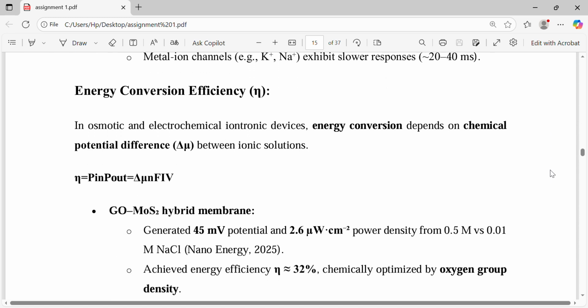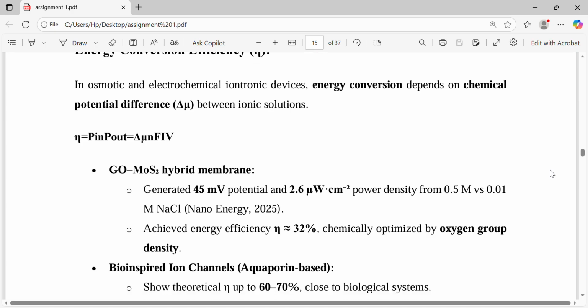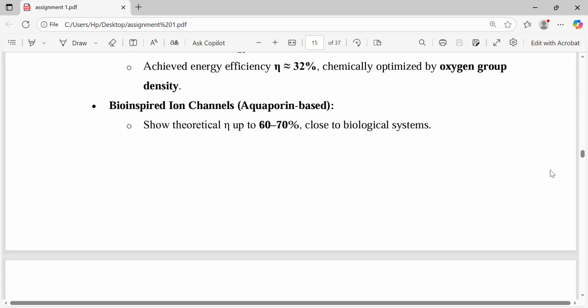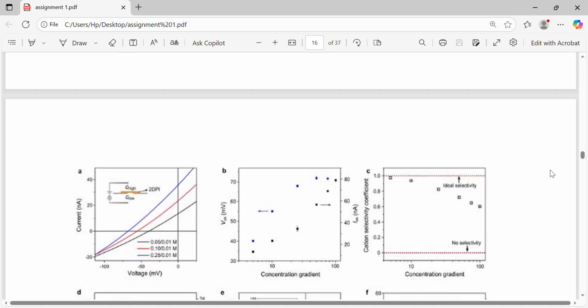Energy conversion efficiency. In osmotic and electrochemical iontronic devices, energy conversion depends on chemical potential differences between ionic solutions. A GO-MoS2 hybrid membrane generated 45 millivolt potential and 2.6 microwatt per square centimeter power density from 0.5 M to 0.01 M NaCl, achieving energy efficiency of 32%, chemically optimized by oxygen group density. Bio-inspired ion channels show theoretically up to 60 to 70%, close to biological systems.